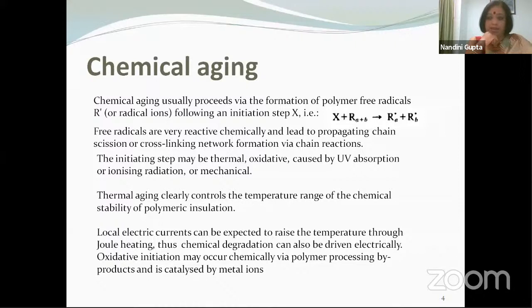Remember, in a dielectric, even under normal conditions, you would have some leakage currents, and local electric currents are expected to raise the temperature through I²R heating. So you can also imagine that if you have electrical stresses, you do not need to apply thermal stresses. And when I talk about stresses, I'm talking about normal stresses, not over stresses. If you have temperature, you have a problem. If you have electrical stresses, you still have a problem, because electrical stresses drive currents and currents cause temperature rise. Also, oxidative initiation can occur at higher temperatures.